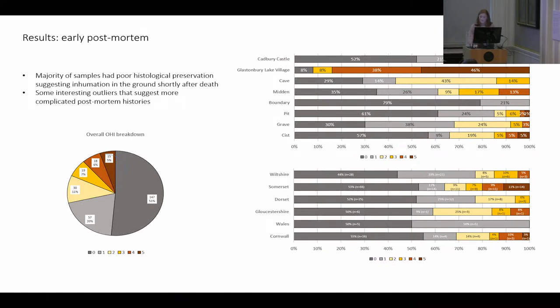So overall, most of the samples had very, very poor histological preservation with scores of OHI 0 to 1, and this suggests that most of the sampled remains were buried in the ground shortly after death and then backfilled, so that the bodies decomposed very slowly, allowing the bacteria to infiltrate and destroy the bone microstructure. There are quite a few interesting outliers, though. About a quarter of the samples had something else going on with them, and we'll talk about these in a little bit.